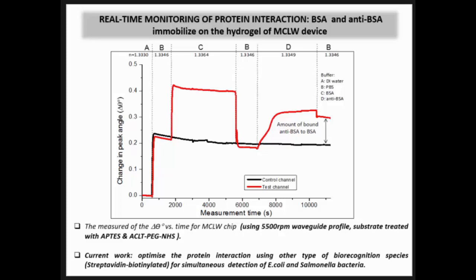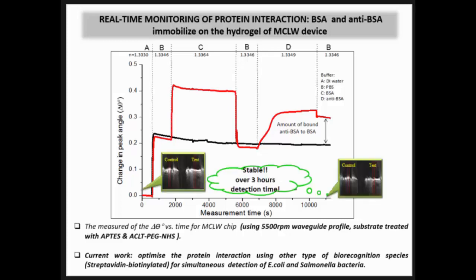So this is the amount that we can convert to study how much anti-BSA can bind with the BSA. This is still an ongoing project, whereby after this we need to immobilize the secondary antibody on top of the anti-BSA with the bacteria. Above 3 hours, the signal is strong, and this is proof that surface modification of the substrate itself can also influence the sensitivity and the stability of our device.